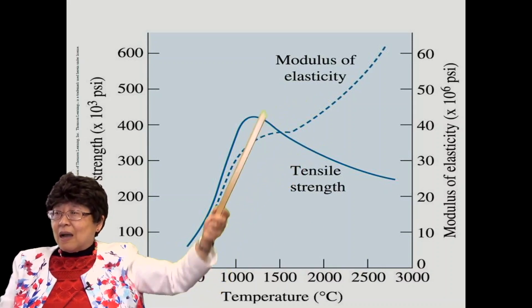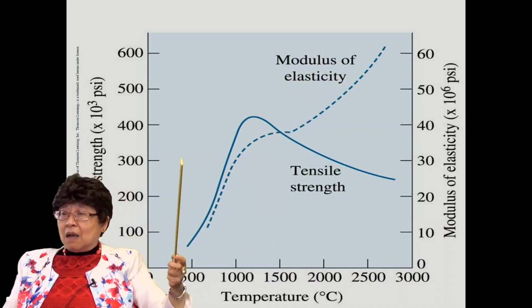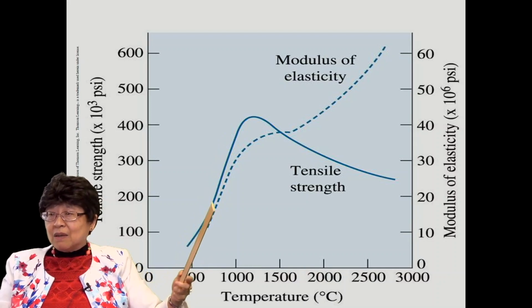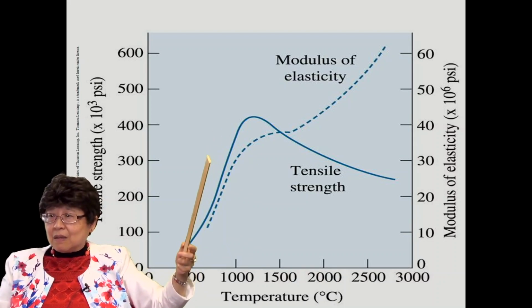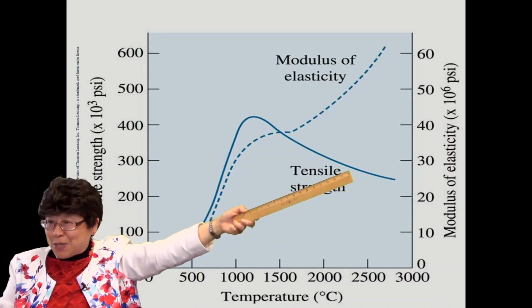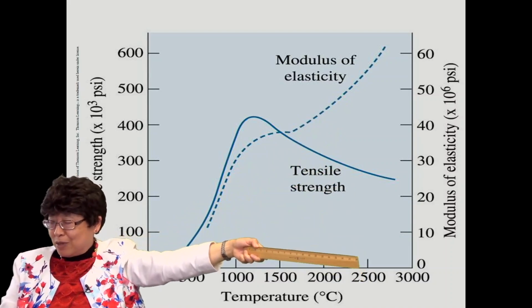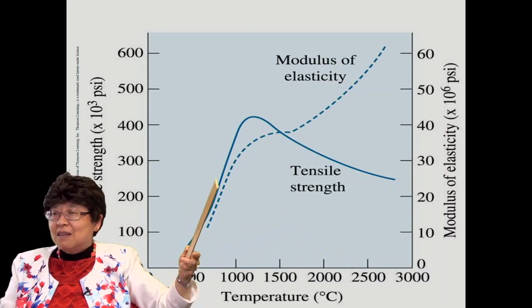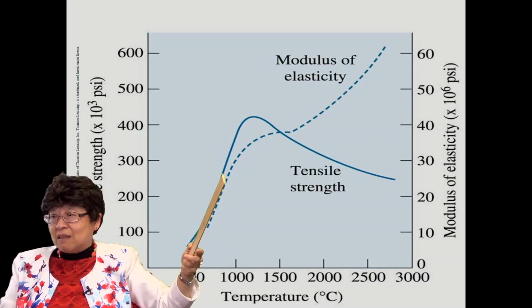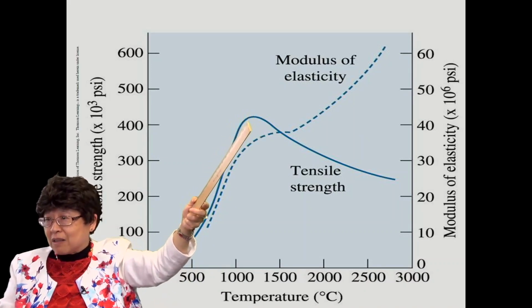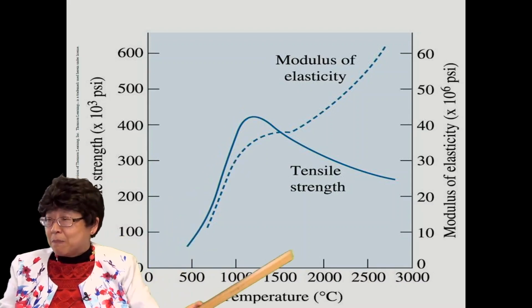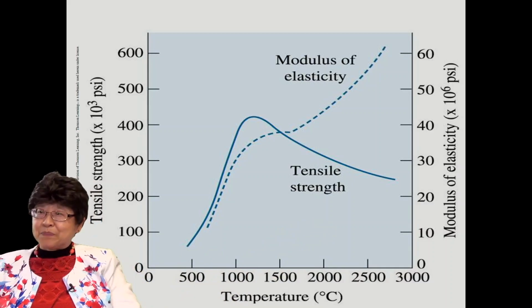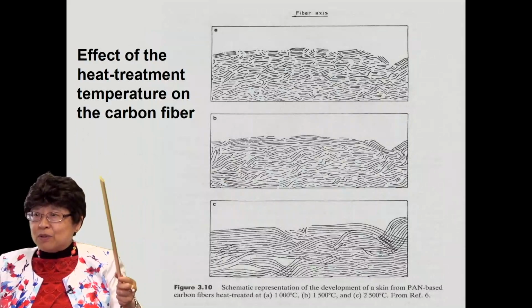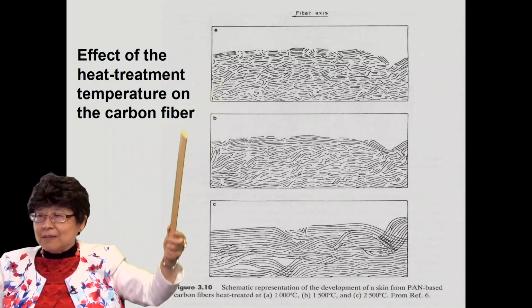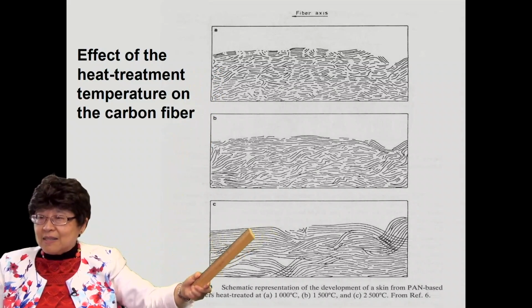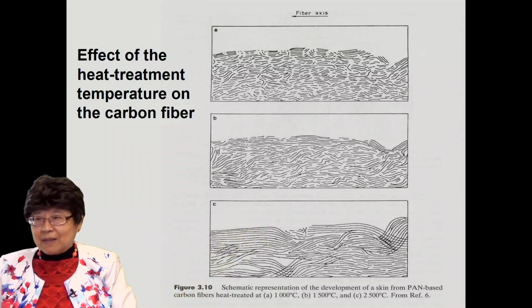So you would have high modulus fiber here, but low strength fiber. This is high modulus and low strength, right? High modulus and low strength if you have a high temperature heat treatment. But if you have a lower temperature kind of heat treatment, the modulus is low, the strength is so-so, but actually here you can have maximum strength. So here would be high strength, but low modulus. So anyway, you have a gradation of many grades of carbon fibers. And depending on the heat treatment temperature, you have the carbon layers looking different. Okay? The higher the temperature, the more extensive and the more parallel and more flat are the carbon layers.